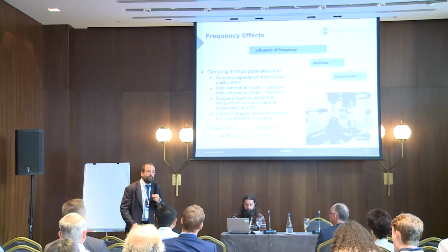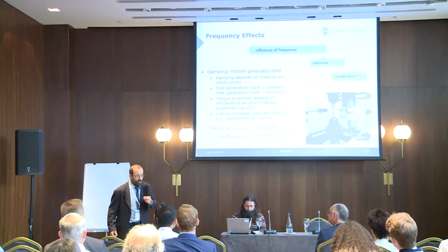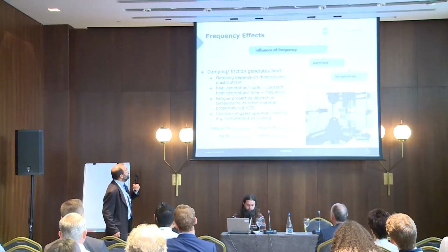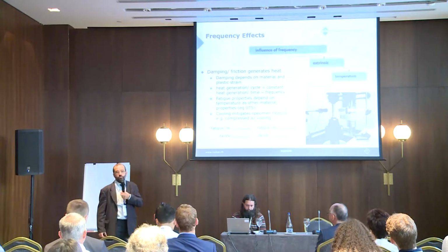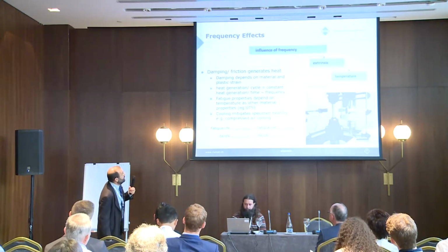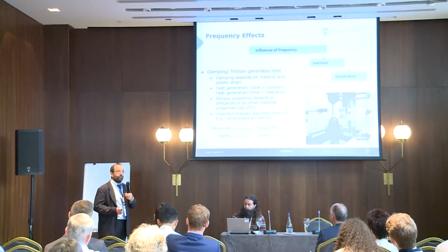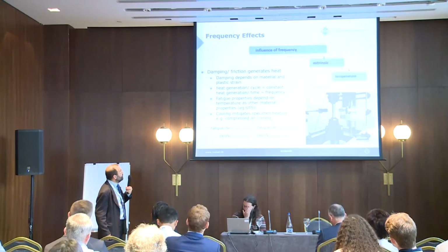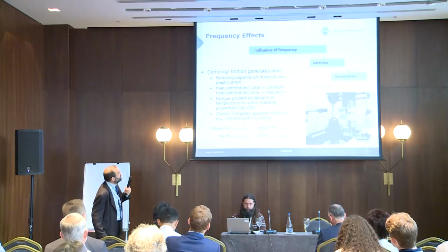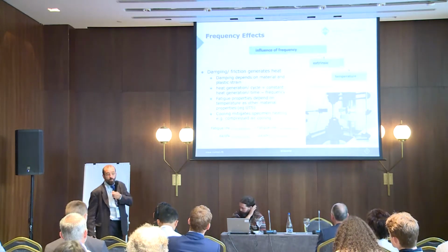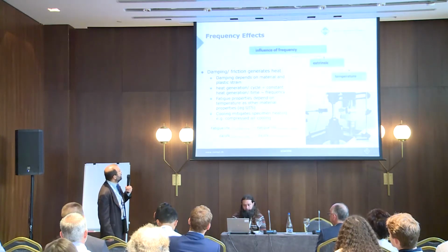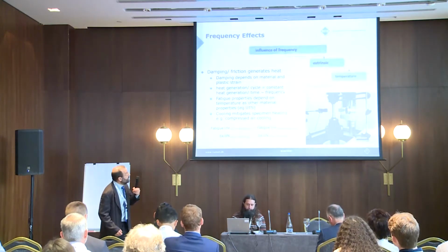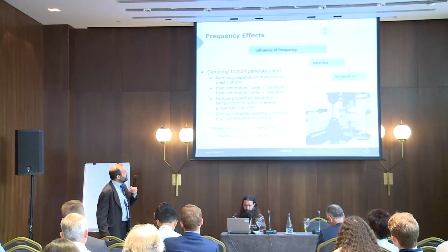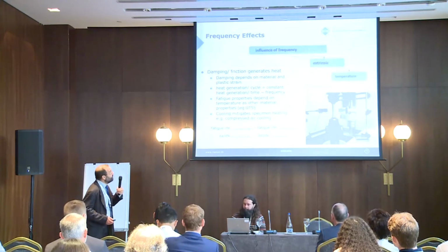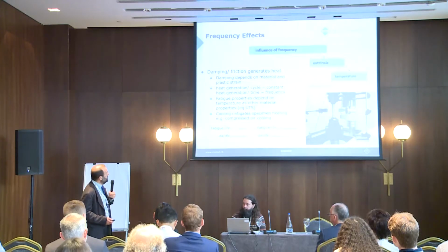So the generated heat is constant for one cycle, and as a result, the generated heat per time is proportional to the loading frequency. The temperature then, of course, also depends on the heat losses. The heat flows to the fixture and to the air, which also depends on the material, of course. So using compressed air is a very efficient method to cool down the specimen in case it is needed because of heating up.